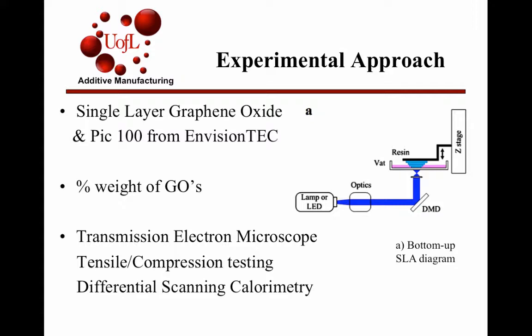The one they used for this was liquid preparation. That's basically where you dissolve the graphene in some kind of solvent. For this one, I think they used, I can't remember, it was some kind of alcohol. They dissolve it in the solvent and then mix it with liquid polymer, and then in an ultrasonic vat. A lot of the reaction takes place in the liquid form, and then it's transferred to the printing process.